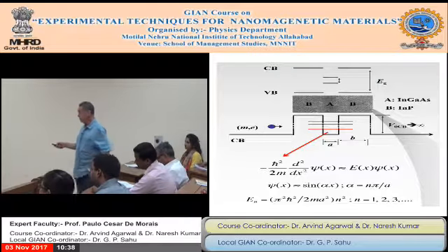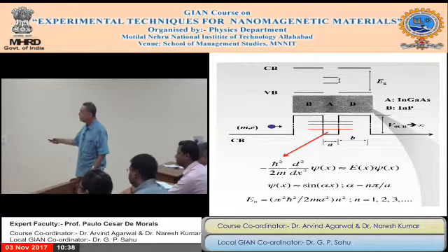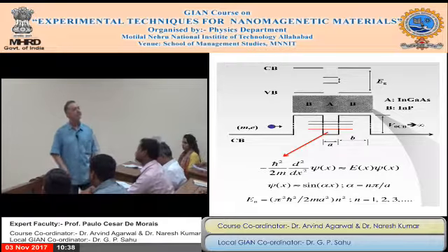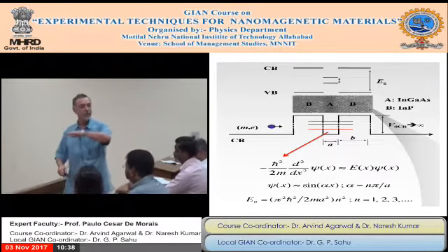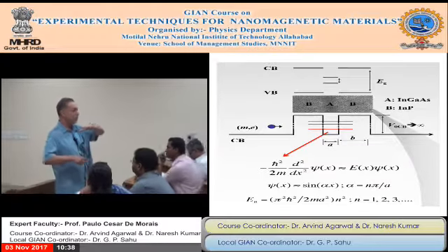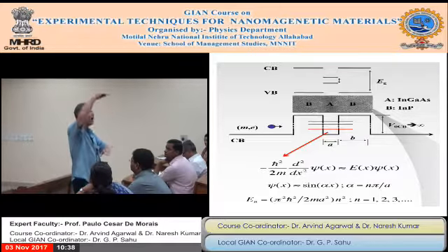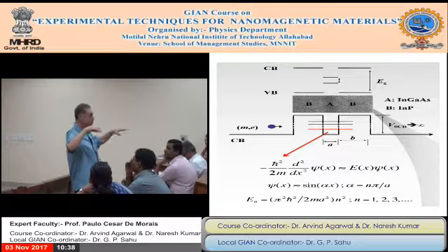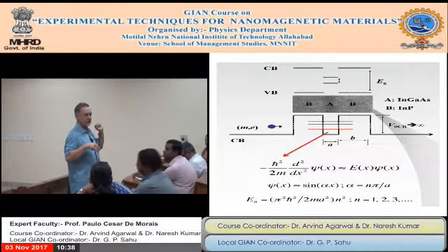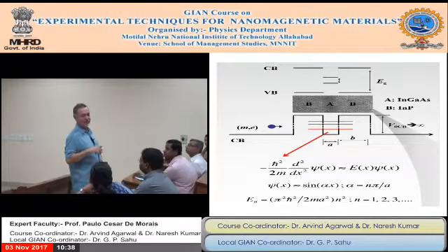So how can you fabricate this in real life? Yeah, you can do it. Let's say you can fabricate layers of semiconductor. Let's say you take a substrate and make a deposit of one semiconductor with wide band gap. You stop growing that and start growing a layer with narrow band gap. And then you stop that and grow a wide band gap layer again. You make this.